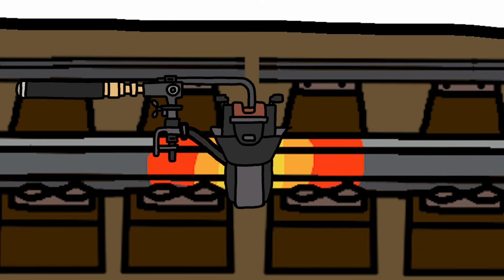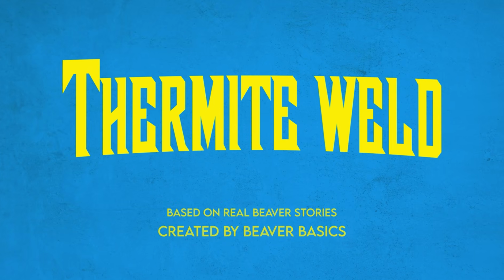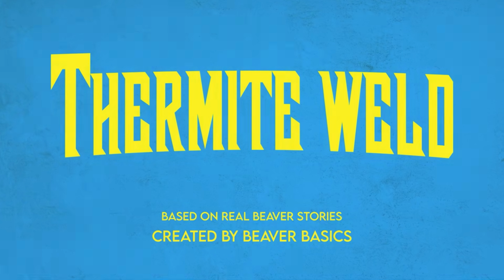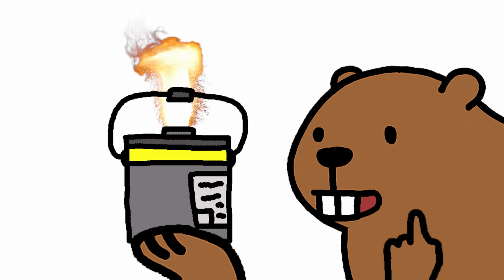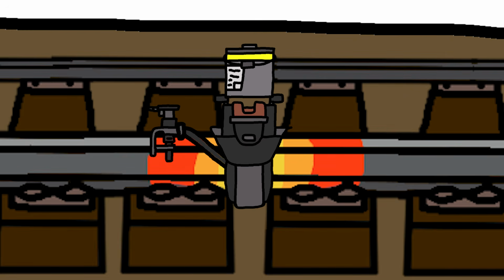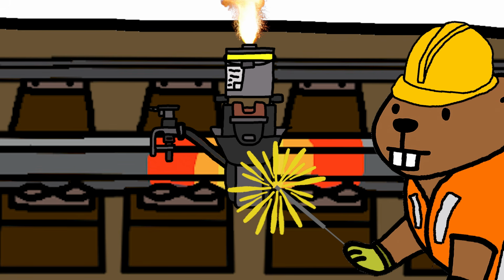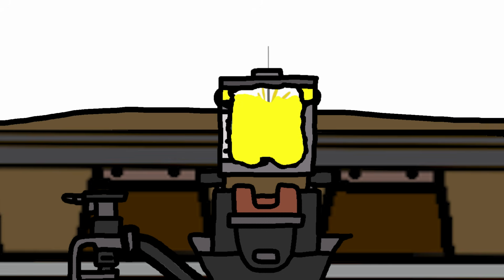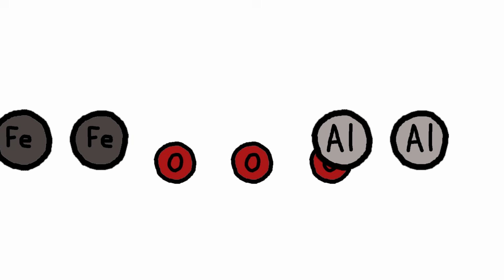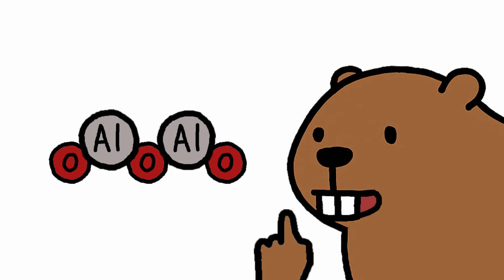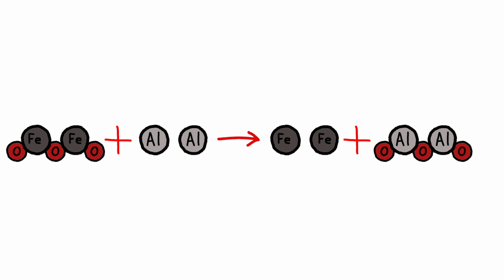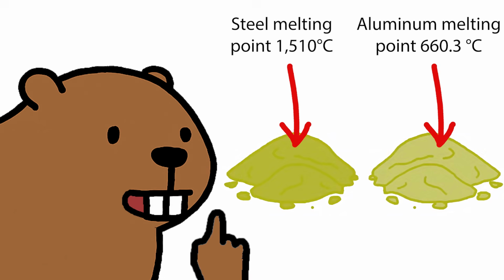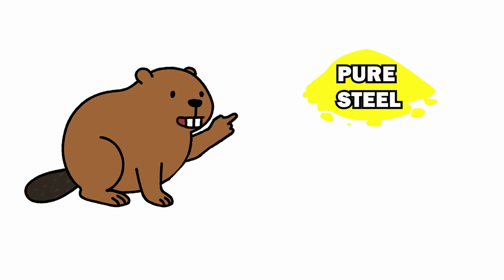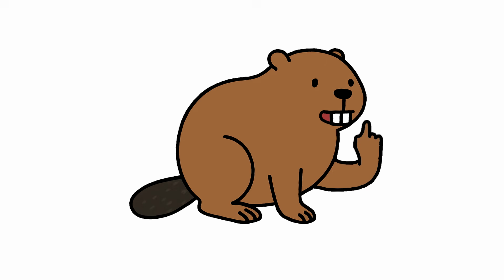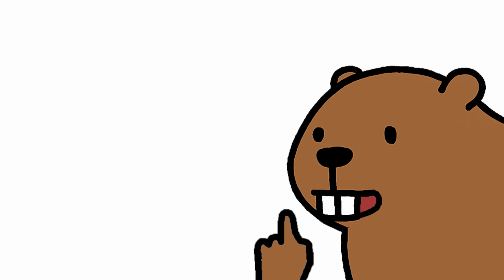Anyways, the preheat is done. Now, the thermite container, also known as a crucible, is then set and ignited by a magnesium ribbon, causing a chemical reaction where the steel oxygen atoms switch places with the aluminum, as aluminum is more reactive and forms stronger bonds with oxygen. When these bonds form, they release a great deal of heat, hot enough to melt the two metals, forming pure molten steel and pure aluminum oxide. This chemical reaction is also known as an alumothermic reaction.